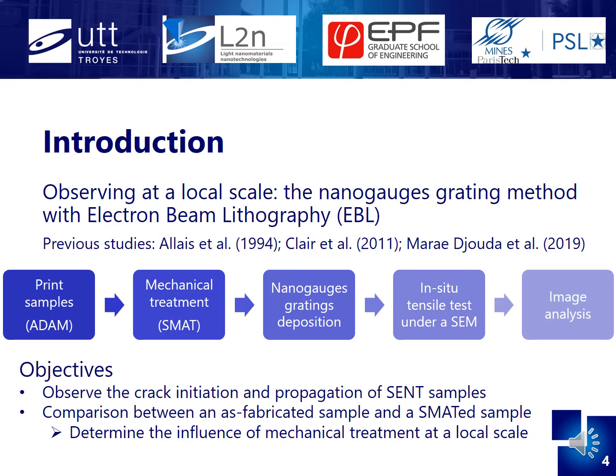Previous studies used the electron beam lithography process to apply at the surface a periodic grating made of nanoparticles, and conducted an in-situ mechanical test under a scanning electron microscope, or SEM. Images are recorded depicting the evolution of the nanoparticle displacements in order to analyze microstructure features. The same method was used in this study. The main steps are: the printing process with the ADAM technique, the mechanical treatment with the SMAT, the nanoscale grating deposition through the EBL process, the in-situ tensile test under SEM, and the image analysis after the test. The main objectives are the observation of crack initiation and propagation of single-edged notched tension specimens, in order to establish a comparison between an as-fabricated and a SMAT-ted sample, and to determine the influence of such treatment at a local scale.